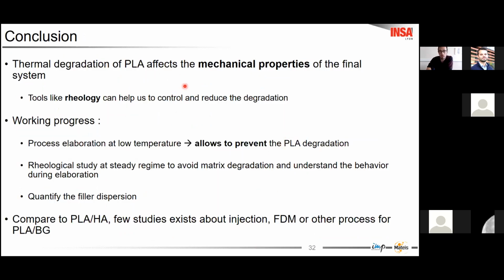As observed in literature, this type of material remains very interesting for bone regeneration applications. Tools like rheology will allow us to better control the degradation and mechanical properties of this composite. Our ongoing studies include thermal processing at low temperature to prevent PLA degradation, and a rheological study in the nonlinear regime. We can see there's a need to better understand the interaction between the matrix and the filler, and the mechanism behind this composite.